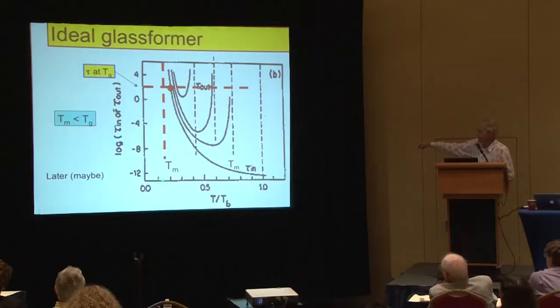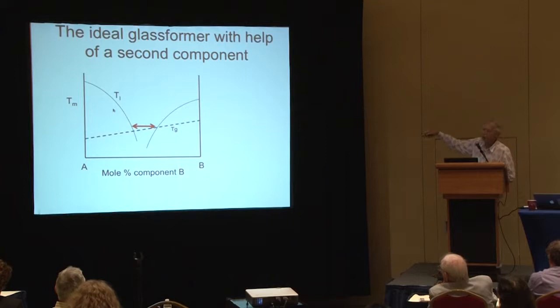And then, in concept, wouldn't it be nice if we could have an ideal glass former where we've managed to push the melting point below the glass temperature, which means we could never measure it? And there is a case in question. Here's the concept diagram where you start with two different liquids and mix them together, and there's a region where the eutectic is below the glass temperature that would define the ideal glass system, and we'd never have to worry about crystallization. How nice that would be, and does it ever happen?